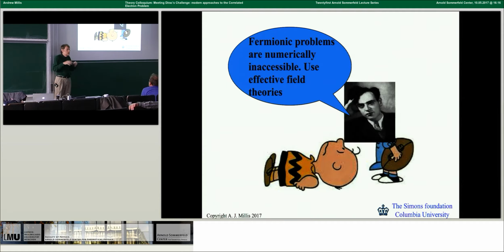And where the interesting physics happens is that as you make it smaller, the number-phase uncertainty relation becomes more important. Or to put it slightly differently, the charging energy of these small grains becomes important. So you start to see stronger quantum and other fluctuations of the superconducting phase. And studying exactly what those things do is a very interesting area of physics.